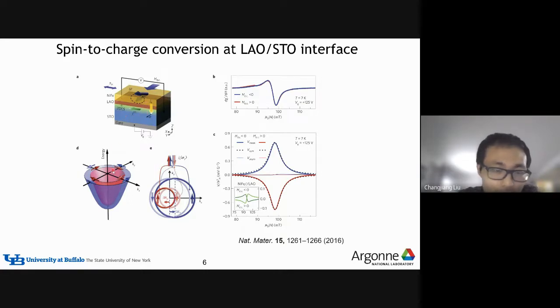And then due to the spin orbit coupling, specifically at this interface, it is due to the inverse Edelstein effect. Basically, because there is a spin momentum locking. And once you have a spin polarized current, that spin polarized current can be converted into a net charge current. So eventually, people can observe a large voltage just due to the spin current. And they found that this spin Hall angle can also be tuned by applying a gate voltage. So very interesting. So these are just two examples.